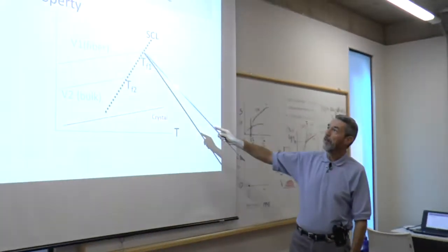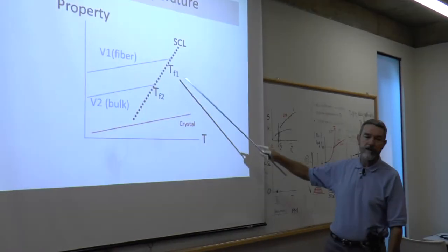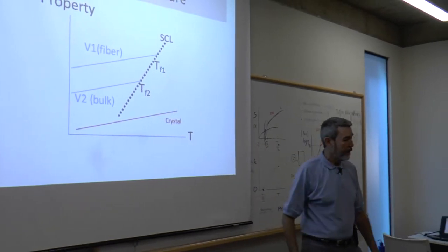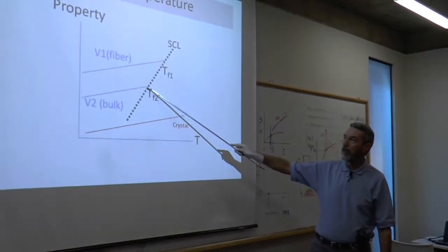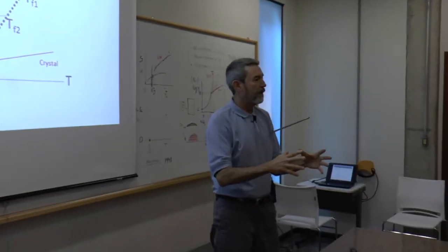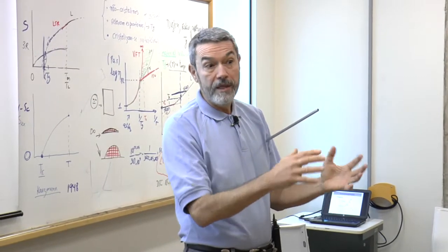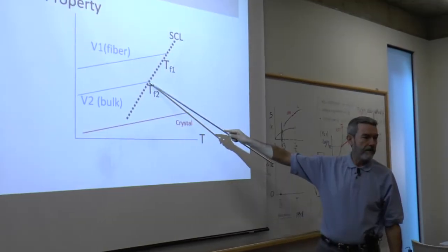So we have a fiber with a fictive temperature very high. And then the same liquid, the same composition, cooled much slower, like to produce a very large chunk of glass, a bowl of glass. Of course, the cooling rate, at least of the interior parts, will be much, much, much slower. So the same material can have two widely different fictive temperatures.